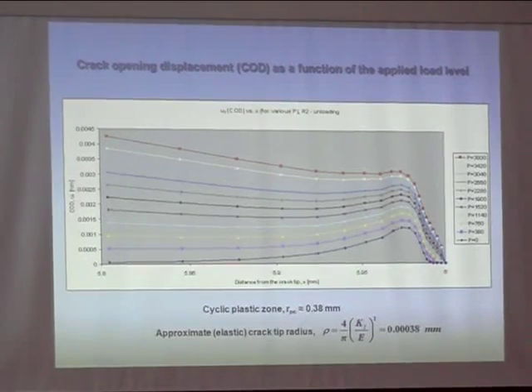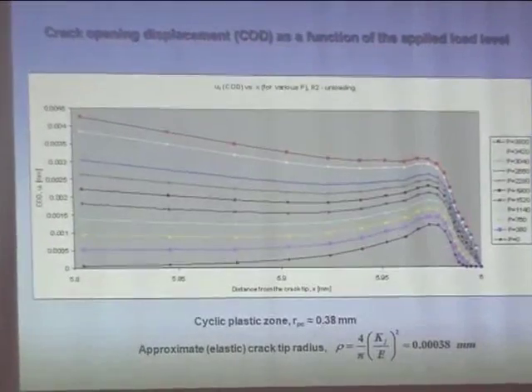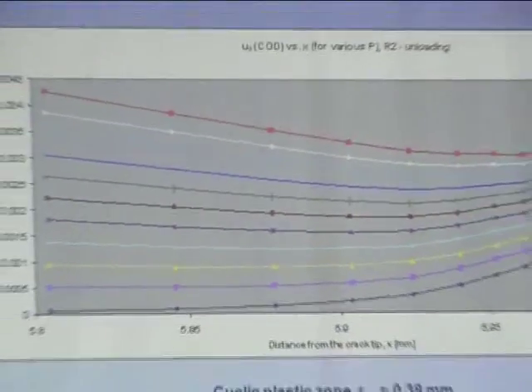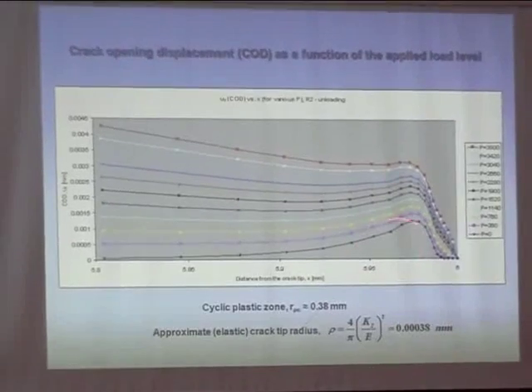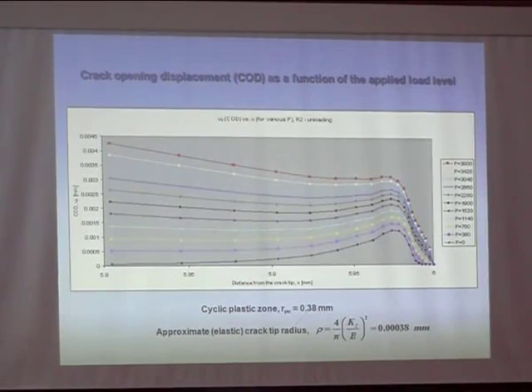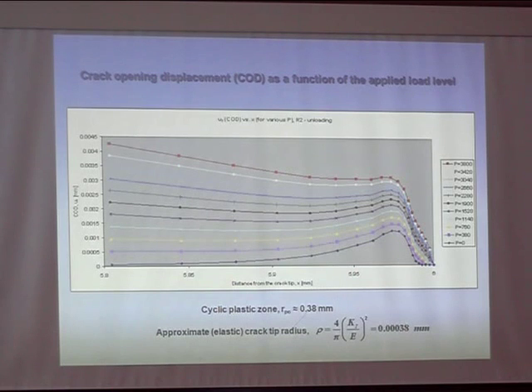No, the crack tip is here, that's the opening, and the stress field will be here. Yes. This opening we have also seen experimentally, and it must occur. Otherwise, you would never see a closure behind. Furthermore, you need this volume here for the representation after. This is the emptiness. So I concluded that I can model the crack as a crack with a radius, always an empty hole. Even if you apply compression now, you will get a nice hole here with the concentration of 3. That's what my computer says and my model.